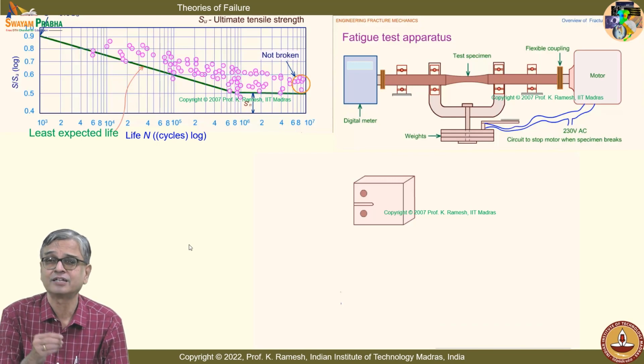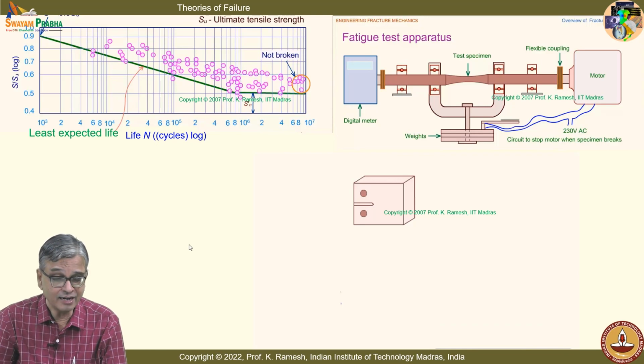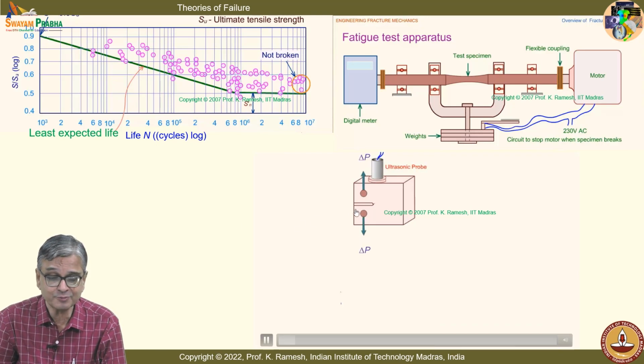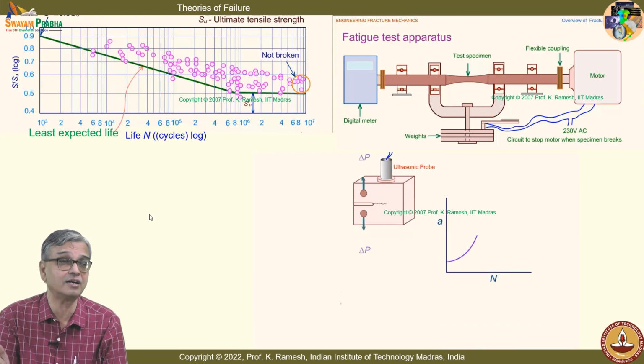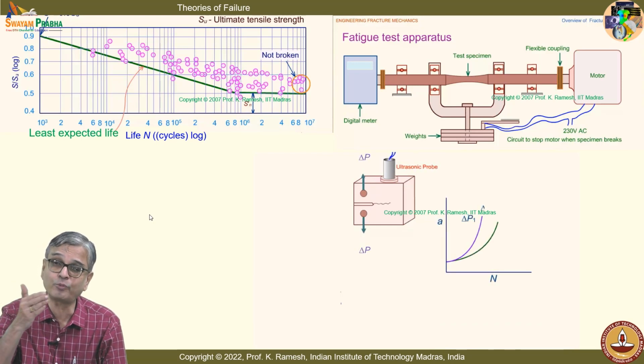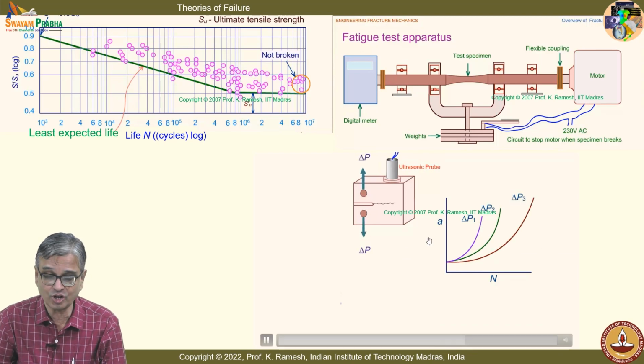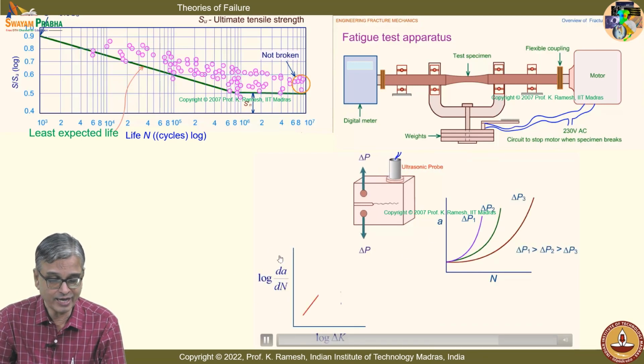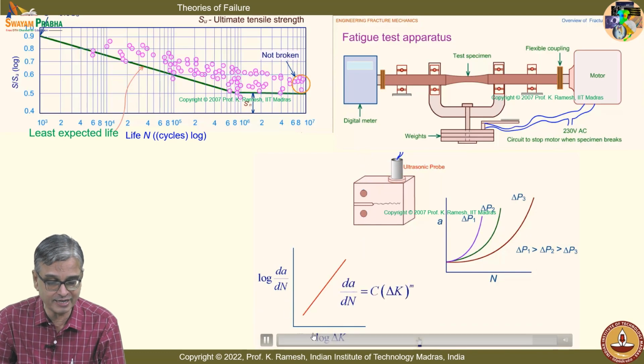Suppose I ask a question: all the failures, how do they generate? You have a crack, and the crack grows on the surface and fractures. If you ask, can I monitor how the crack grows? You can't answer unless you develop another test where I have a specimen with a crack and an ultrasonic probe to find out how the crack grows, and then I plot crack growth curves. From the crack growth curves, I post-process, and you have log dA by dN versus log delta K, which becomes a straight line. This is known as Paris law.